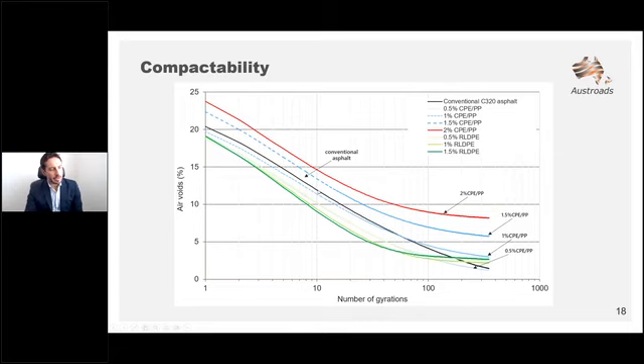And the black curve is actually the way standard conventional asphalt is compacted. So you have the air voids on the y-axis and the number of gyrations on the x-axis. And if you focus on the blue lines, these are the ones related to the post-consumer type of plastics at 0.5%, 1%, 1.5%, and then 2%, represented here in red. That was kind of our maximum limit, and we have excluded that from the experimentations, as I said, because it was quite tough to compact.